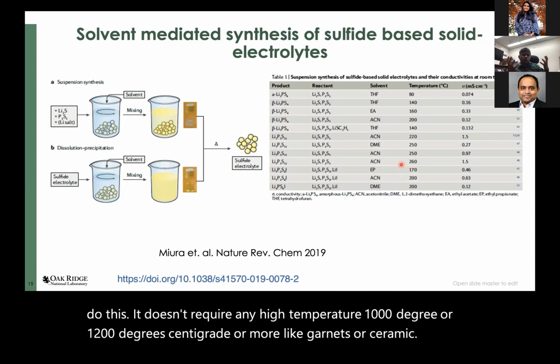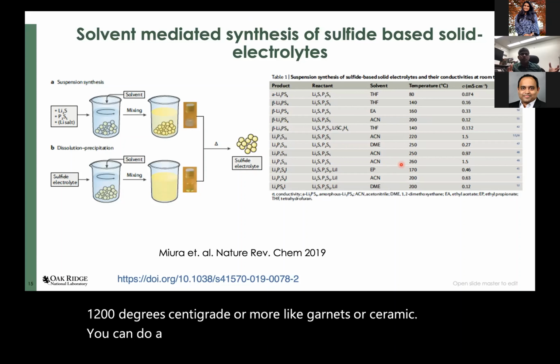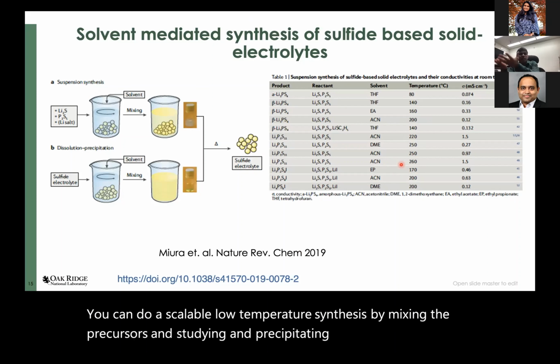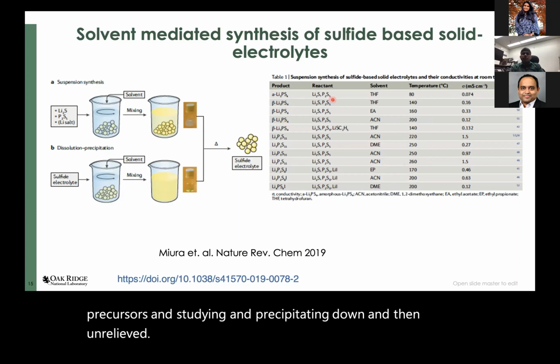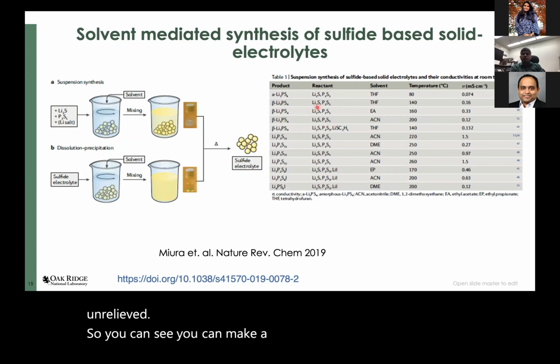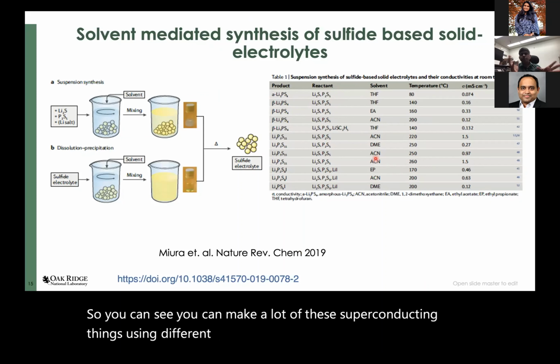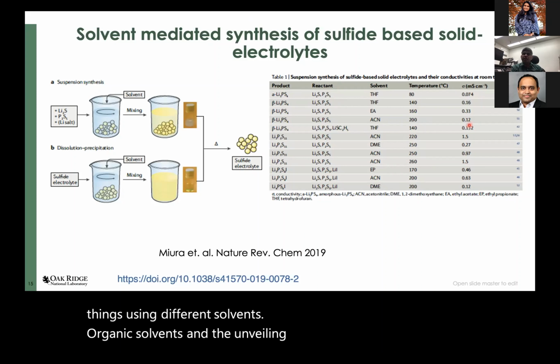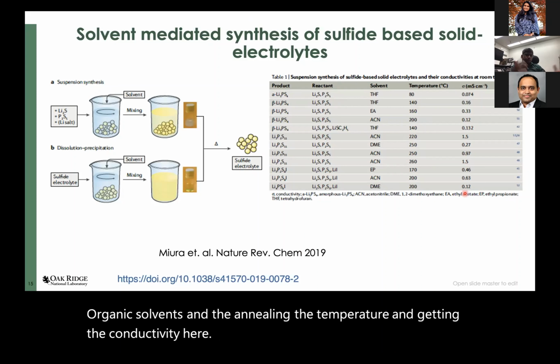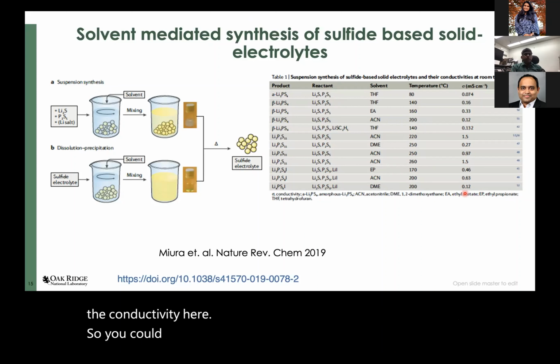You can do a scalable low temperature synthesis by mixing the precursors, stirring and precipitating down, and then annealing it. So you can see you can make a lot of these superionic conductors using different organic solvents, then annealing at a temperature and getting the conductivity here. So you can start making these electrolytes reasonably well.